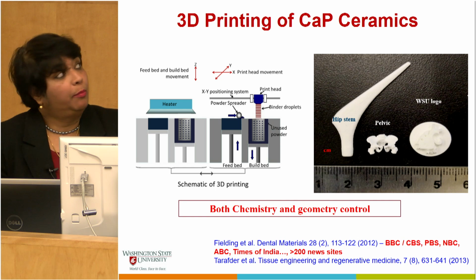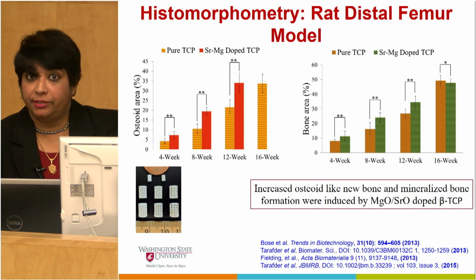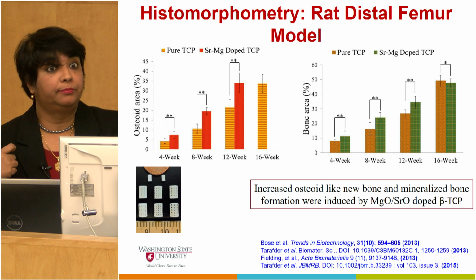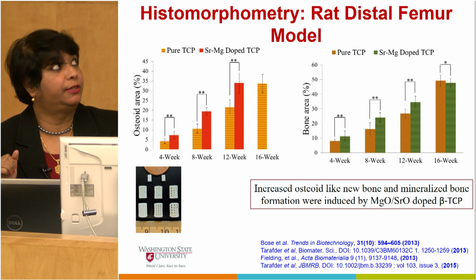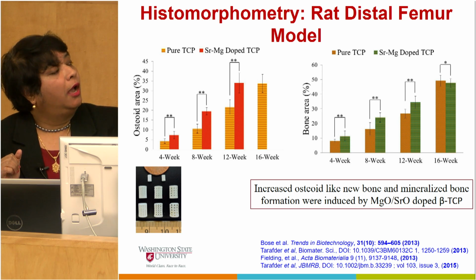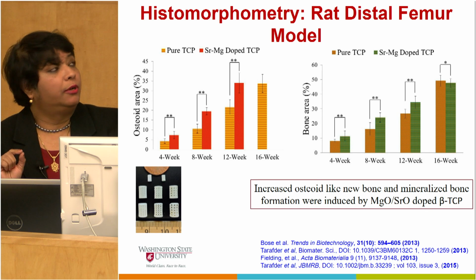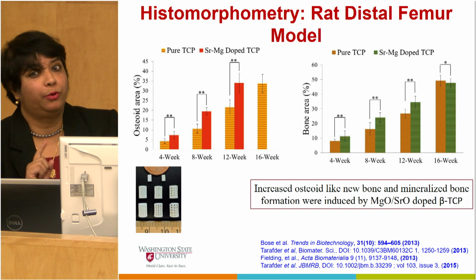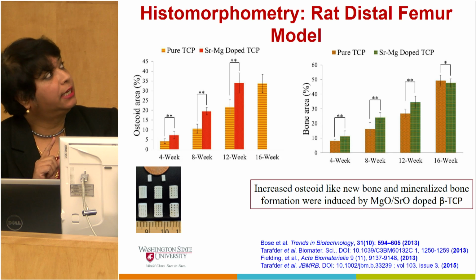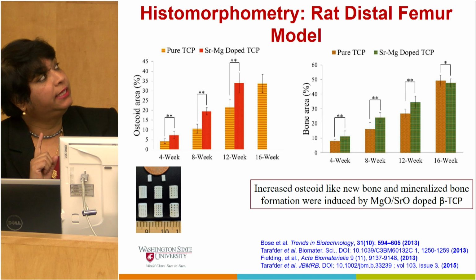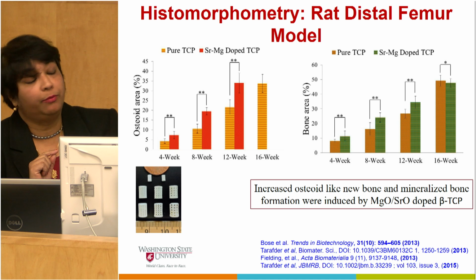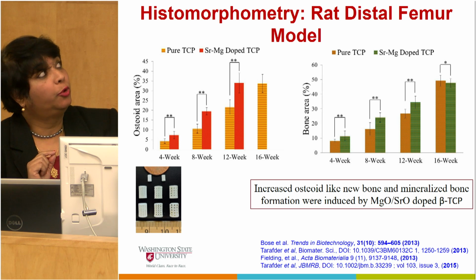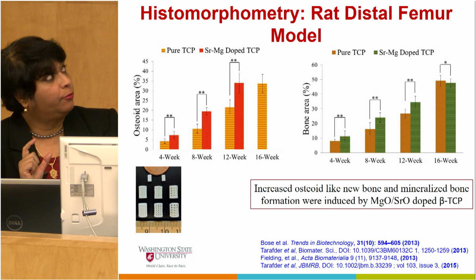So we made some simple scaffold parts from calcium phosphate, which is a bone-like material, as we have in our bone, about 70% of our bone. I'm going to point out the areas where you can focus. The orange color is the control sample, and the red color is the chemistry modified calcium phosphate. We did this study using a rat distal femur model to show how bone growth takes place within this porous 3D printed bone-like scaffold.